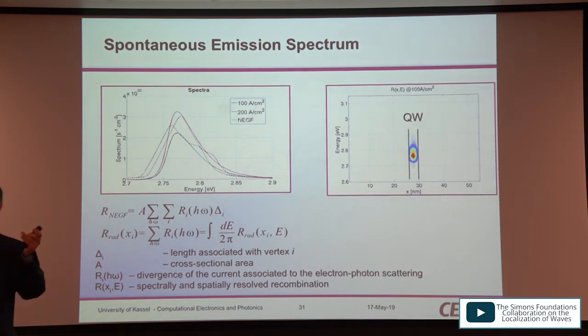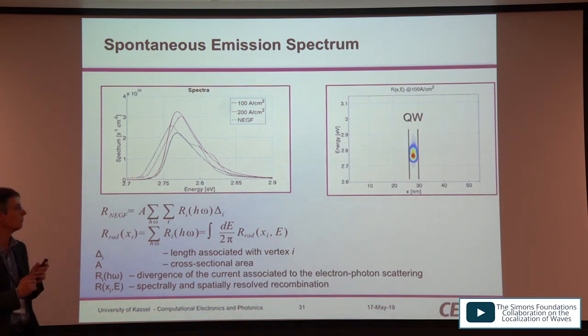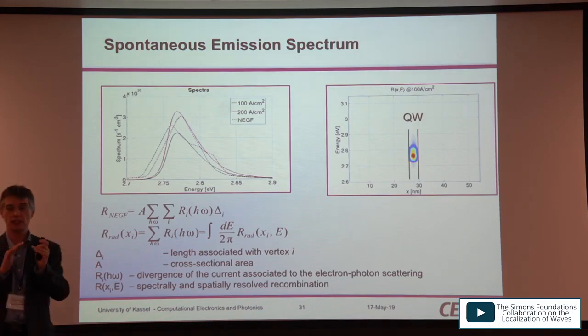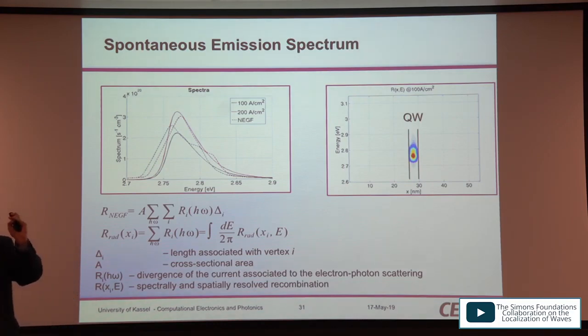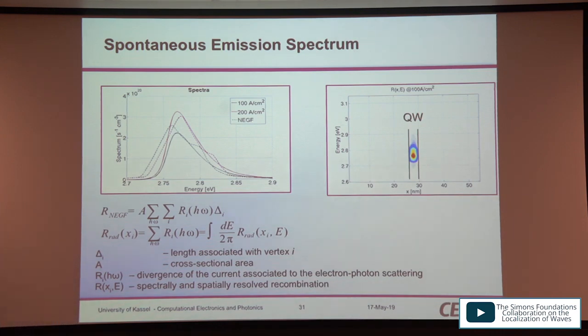The tunneling of carriers into the band gap. So that's naturally included, of course, without any fluctuations, you know. And what we also saw is that this depends a lot on the discretization we do in energy space in the band gap, but again, the effect is included. Also, the amount of radiative recombination is similar to what we see in the drift diffusion simulation, and that we compared a little bit more in detail.